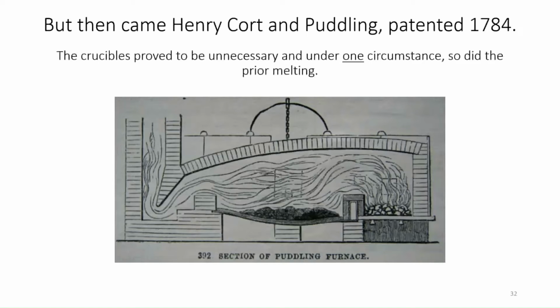Henry Cort, well, basically he showed that you didn't need the crucibles, that actually you wouldn't get sulfur in your iron, which is what the big fear was, that you could just simply rabble the iron around in the bottom of the reverberatory furnace. And very quickly, it was demonstrated that this was an amazing way of making bar iron, because it removed the phosphorus. And that's the key part of the puddling process, which is not always observed.